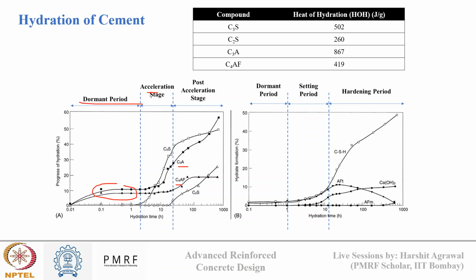Then in the acceleration period, we see C3S also starts to react, and finally in the post acceleration period, C2S also starts to react. So you can see here, this is the progress of hydration and this is hydration time. C2S shows growth in hydration in the post acceleration period, while in the acceleration period you can see a major rise in the hydration of C3S. Okay, while in the second figure you can see the amount of hydration product that is formed over time.